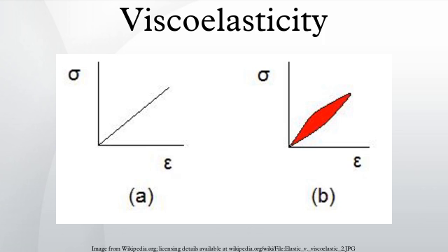Some phenomena in viscoelastic materials are: if the stress is held constant, the strain increases with time; if the strain is held constant, the stress decreases with time. The effective stiffness depends on the rate of application of the load. If cyclic loading is applied, hysteresis occurs, leading to a dissipation of mechanical energy. Acoustic waves experience attenuation. Rebound of an object following an impact is less than 100%. During rolling, frictional resistance occurs. All materials exhibit some viscoelastic response.